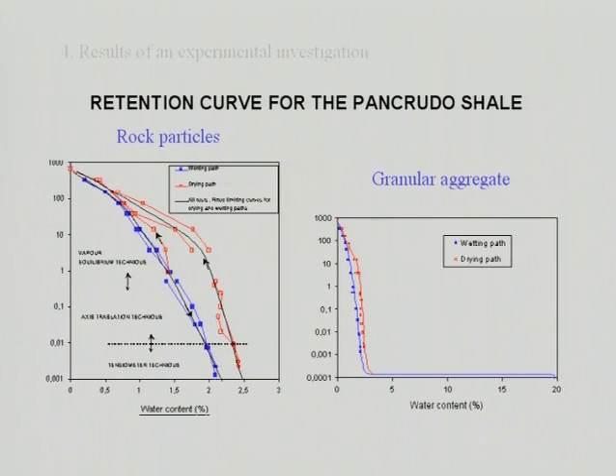However, if you consider the whole picture, I mean the aggregate, then of course the porosity is much bigger, and the actual full water retention curve for the whole material is something like that. If you impose a very, very small suction, you essentially drain all the water from the big pores, and only when you arrive at the water content of around, in this case, 4%, then you have this change in the shape of the curve, and certainly you have to reach very high suctions, 1,000 megapascals, in order to really dry this rock.